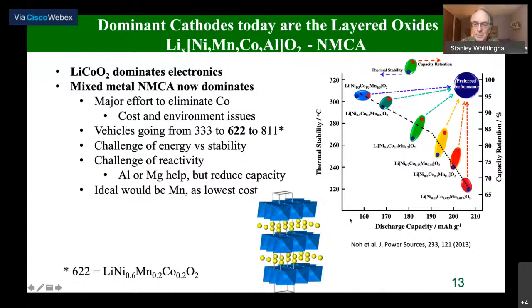So let's look at this now famous plot out of South Korea. If we look at the equimolar material, that's 1/3 nickel, 1/3 cobalt, 1/3 manganese. It has the lowest capacity, 160 milliamp hours per gram, but is stable to over 300 degrees centigrade. If we go to the highest nickel material, which is about 85% nickel, you see it now has about 208 milliamp hours per gram, so much higher, but its thermal stability is only 220. So it's 100 degrees less thermally stable. And what this means is the less thermally stable it is, the more reactive its surface is, so the more likely it is to react with the electrolyte. And you see plotted on the right-hand side is capacity retention.